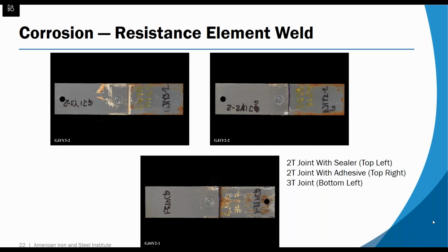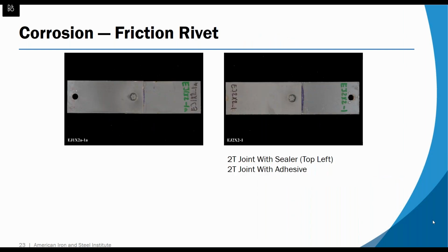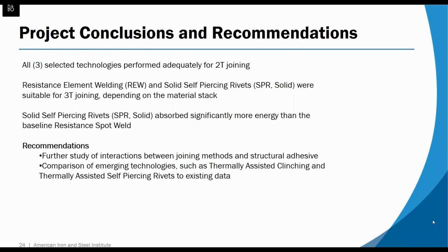Again, you can see the outline where a little bit of white corrosion is coming up around the steel element, but there's no red rust or degradation to the joints. The friction rivet also shows no real effect from the corrosion testing. So all three of these mixed material joining methods can reasonably be said to have mitigated the galvanic corrosion concerns.